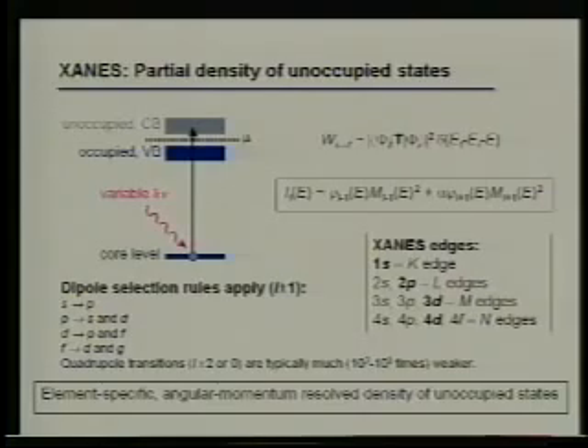In this box here, the 1s state is called the K-edge. Now if you go to the next orbital, the n=2 orbitals, you can have excitations from the 2s, the 2p3/2 and the 2p1/2. The p levels are spin-orbit split. These are transitions from the 2s, again, to P, but from the 2p3/2 and the 2p1/2 it is from P to either S and D states. And so on. From D, you can go to P and F. You can actually get quadrupole transitions, that's for L plus or minus 2, but those are very, very weak.